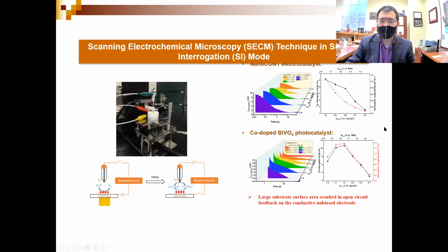Recently, we studied the electrode material with an advanced electrochemistry technique called scanning electrochemical microscopy, which utilizes a very sharp microscopic sized electrode, a nanoelectrode, to probe the surface of your electrode material by scanning the surface of the sample with a scanning probe, so that their surface active species coverage and also the activity can be identified using this technique.